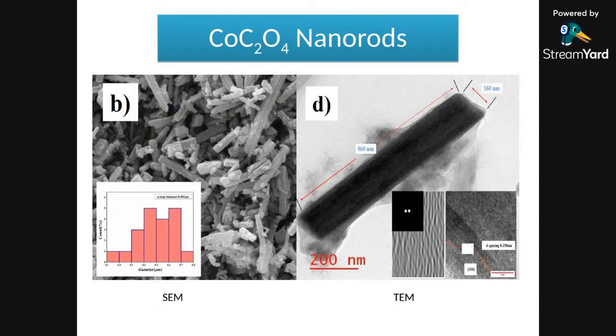We started with the cobalt hydrated oxalate, then we did the complete water removal step, and the material has been converted into cobalt oxalate nanorods. They are not nanorods of a few nanometers, but close to 150 nanometers in depth and around 1000 nanometers in length. So they are actually very bulky rods. They are not exactly in the nano region, but in the sub-micron or micrometer region.